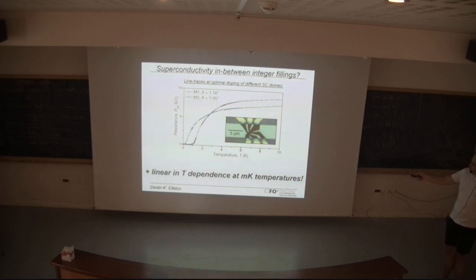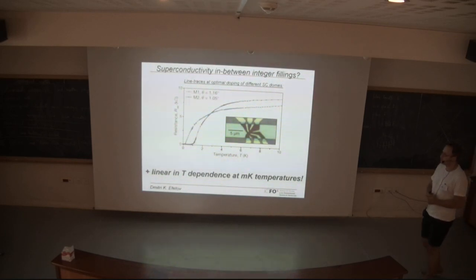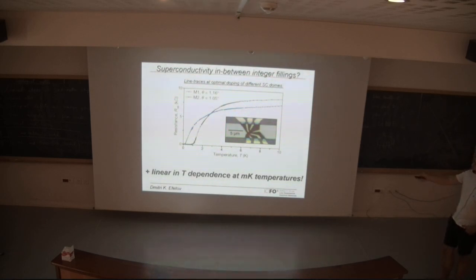You can really see that if we zoom in into these superconducting domes, if we sit at optimal doping, at the point where the superconducting TC is the highest, we can get curves where the resistance goes completely to 0 with temperature. The reason why we call it superconductivity is primarily because we observe a 0 resistance state, as expected from superconductivity. The other thing I want you to pay attention to is that the resistance at high temperature follows a linear temperature dependence, as is probably familiar to many of you, and it is debated right now whether this is a strange metal phase, for example.